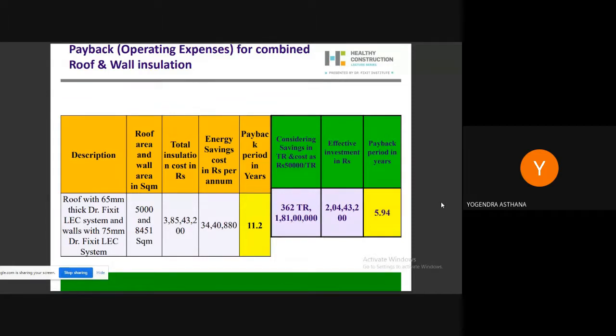So whatever investment we put in installing this insulation, the total insulation cost of providing this 65 mm thick PU foam and 75 mm thick EPS for around 5,000 square meter of roof surface area and 8,451 square meter of wall surface area is coming out to be 3 crores 85 lakhs 43,200. And per annum, per year, we are saving energy of 34 lakhs 40,880 rupees. So if we take energy saving alone, we'll recover our investment in insulation in 11 years.